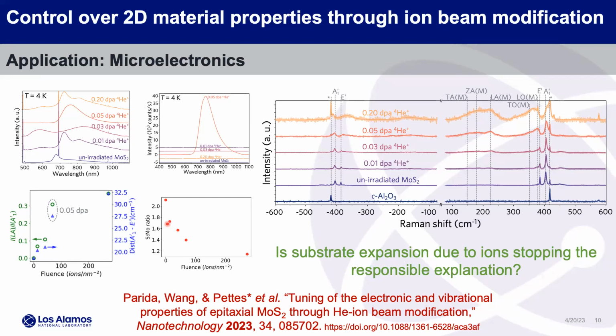We don't have that resolution, but we can pick up differences in sulfur vacancy ratio just by hitting it with lower energy alpha. So the sulfur vacancies go way up, to the point that you start out a little bit above 2, because when these are grown at Penn State, they are grown with about an 18,000 to 1 ratio between sulfur and molybdenum precursor gases. So it's about 2.11, and then it drops off as you would expect for the vacancy, but we still have this outlier at 0.05 dPa.